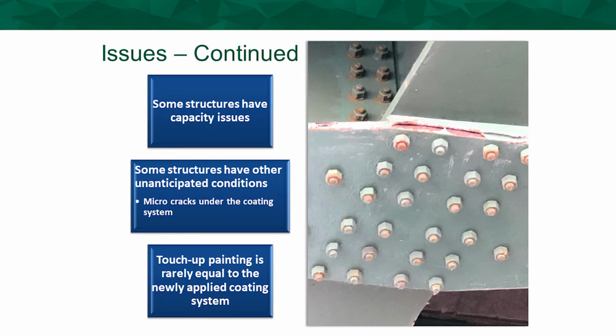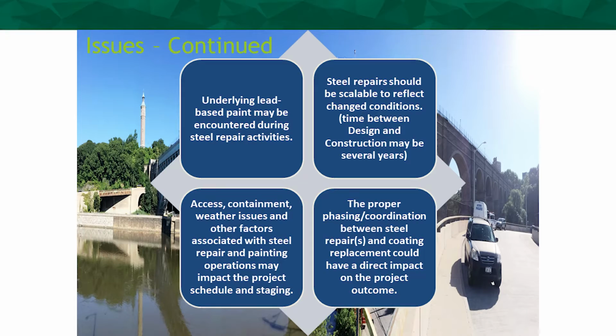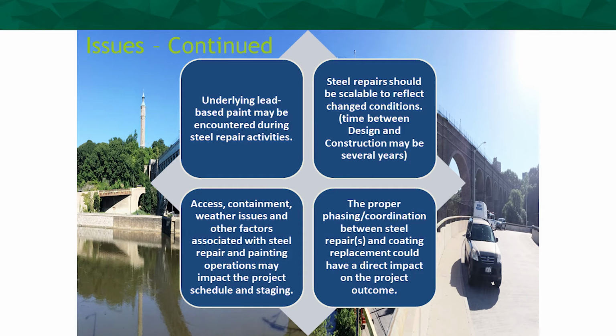And touching up paint is rarely equivalent to the original cleaning and painting of that structure. Those can be considered weak points, and those are the areas that could possibly fail down the road because they weren't cleaned properly, again, where those areas are from touch-up. Other issues are lead-based paint. When you're removing the old steel, removing rivets or bolts, there could be lead-based paint that's exposed from those operations.